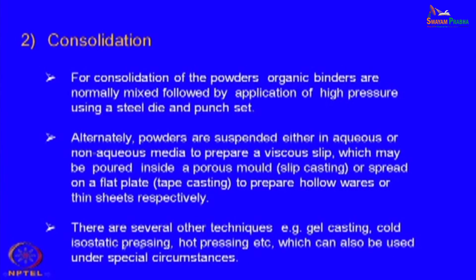This is called cold isostatic pressing; one can also use hot isostatic pressing. You apply isostatic pressure and at the same time simultaneously heat the material to a high temperature. In this case, of course, one cannot use a liquid because it involves high temperature, and therefore one has to use a hot gas environment. Okay. So, hot isostatic pressing is one of the latest techniques, and most of the high performance ceramics are made by this hot isostatic pressing. It is quite expensive, but it has its own advantages.